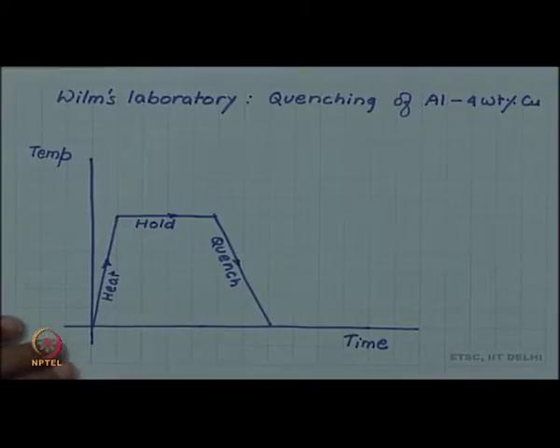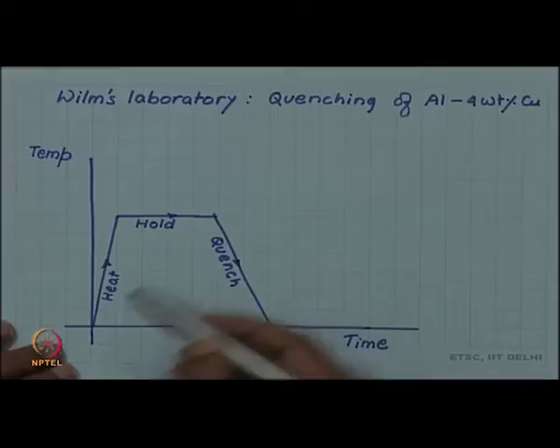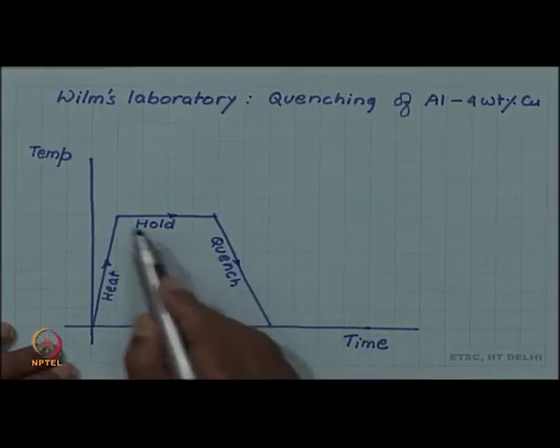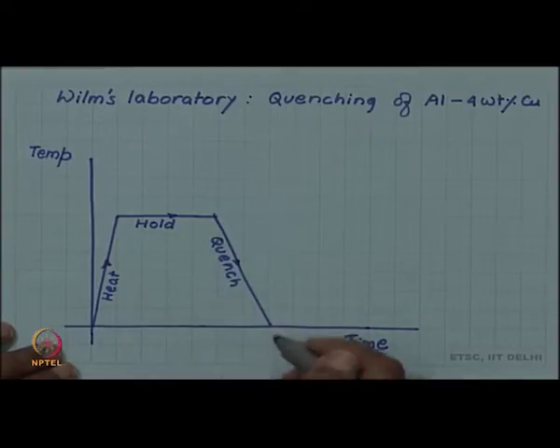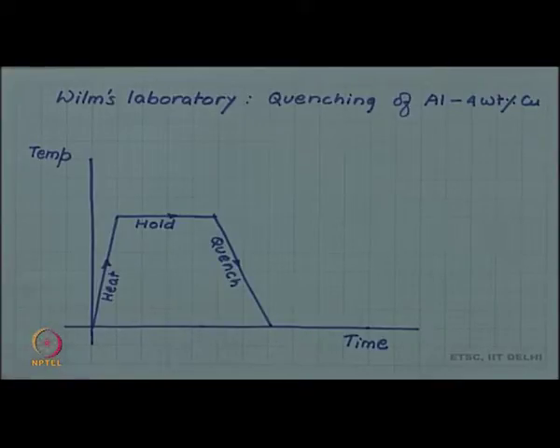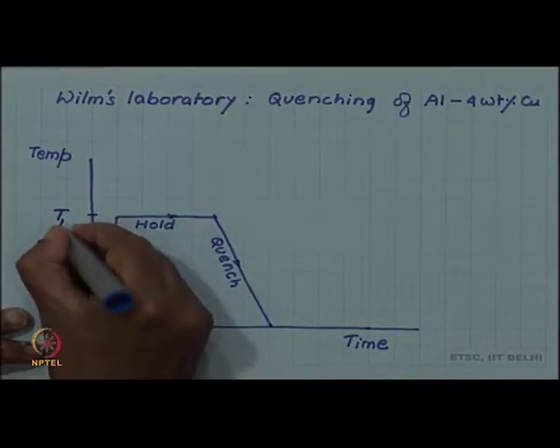So as you know, a temperature and time graph can be made for any heat treatment process. So he planned to heat the aluminium alloy, hold it, and then quench it, and after quenching measure the hardness. And the expectation was that, like steel, maybe the hardness of aluminium alloy also after quenching will increase. So this is the temperature for holding.